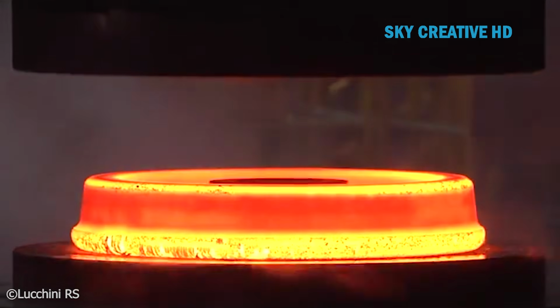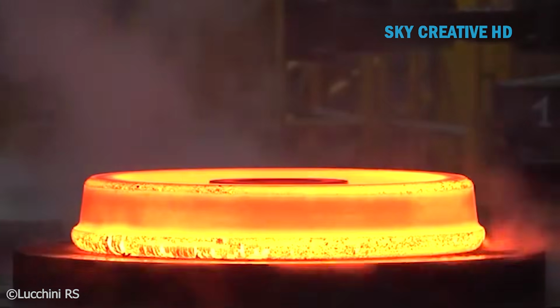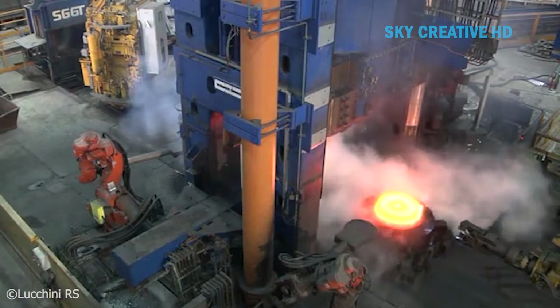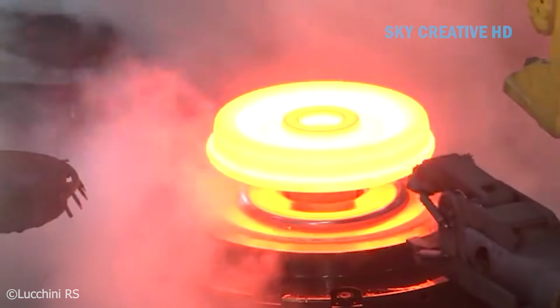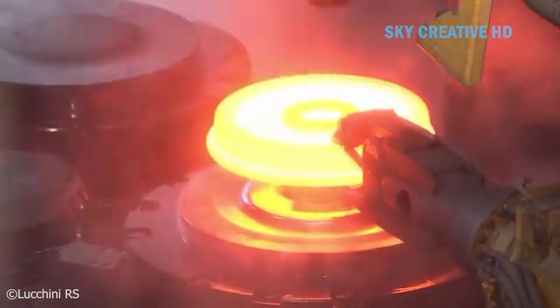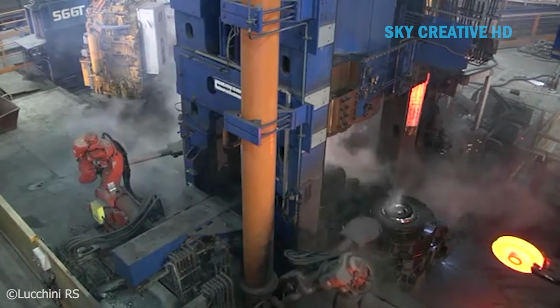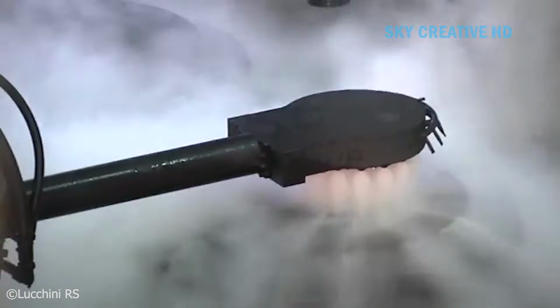The most critical surface is the tread, the part that actually contacts the rail. This surface is machined to a mirror finish, because any imperfection will create vibrations that passengers will feel, and that will cause premature wear of both wheel and rail. The profile is precisely calculated to ensure proper contact with the rail crown, optimizing both performance and longevity.